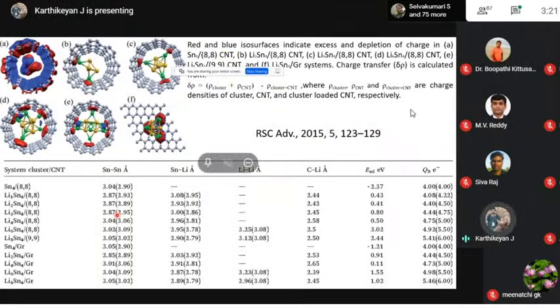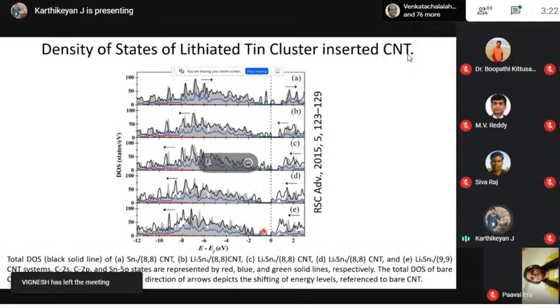composite with the CNTs. And we have actually measured these tin bond, tin-lithium bond and lithium bond. And very importantly, I want to show this lithium bond in an inserted cluster. We can see that the blue charge clouds indicate the depletion of charges. The red one is excess charges. So that means that the lithium bond distance is really decreased when you insert these clusters inside the CNT. That means when you have these clusters inside the CNT, it actually donates some electron to the CNT's pi star orbitals. That we are going to see from the electronic structure calculation.